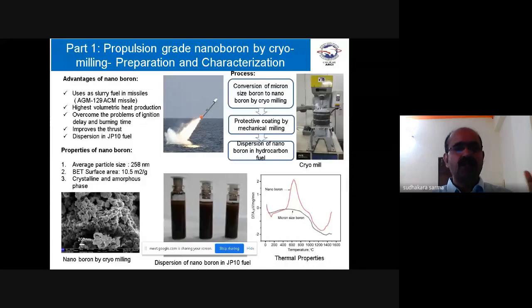Overall, this part 1 of my presentation covers the advantages of nanoboron. Nanoboron is used as a slurry fuel in missiles. The process is conversion of micron size boron to nano size, then making it air stable with a protective coating, and then dispersing this coated nano boron into the JP10 fuel. The particle size by DLS is 258 nanometers, and the BET surface area is 10.5 square meters per gram. Here you can see we checked the performance of the micron size boron and nano size boron. Finally, we dispersed this coated nano boron into the JP10 fuel.